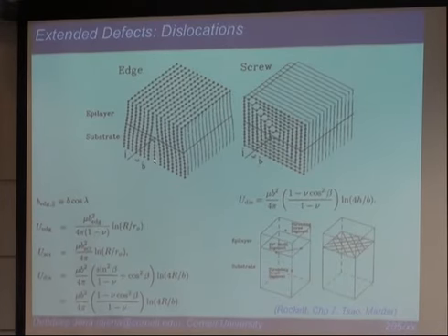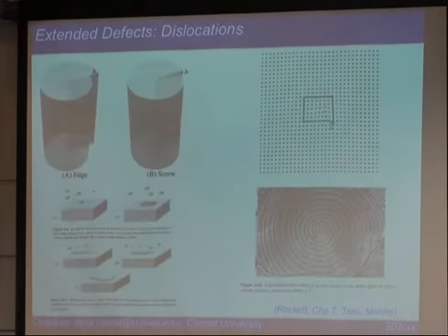So if you take a TEM image of this cross section, you can say, plot me the distances as a function of r in space here: what is the distance between two atoms? You can ask it to plot that distance between two maxima. When you plot it, I think you realize right away that there is a little change going on here inside. Okay, so the question we can ask is, what is the energy cost of forming these dislocations? This is an example of an edge dislocation, and this is a screw dislocation. I had a couple of other pictures last class, which is another way of looking at it. The edge dislocation is sort of like that, and the screw dislocation is like that.